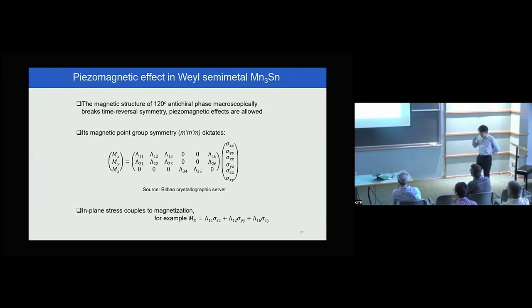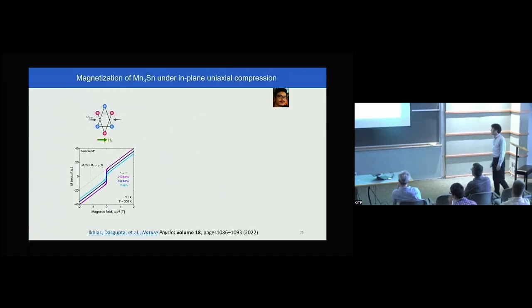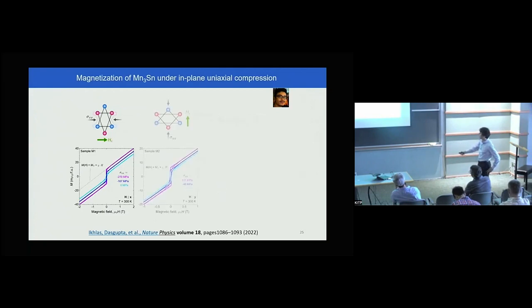So if you actually apply in-plane strain in the material, so let's say Kagome plane, if you squeeze it, magnetization should appear. Let's see. And this is what our excellent former PhD student Equlas has made. He made a very high quality bulk single crystalline sample, applied a uniaxial pressure along in-plane, Kagome plane. Along, say, this x direction or y direction, we found there is almost a similar phenomenon. So what's going on here is the following.